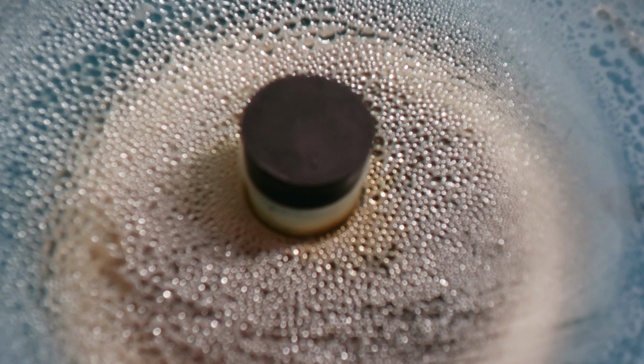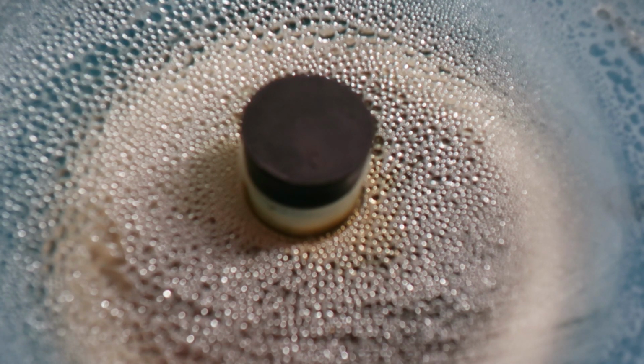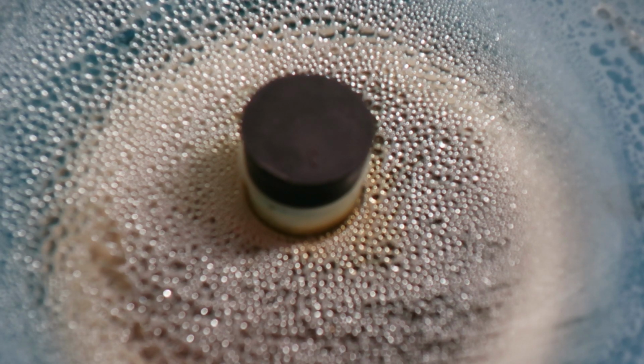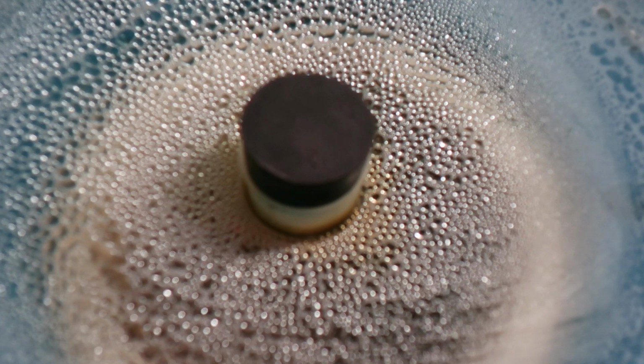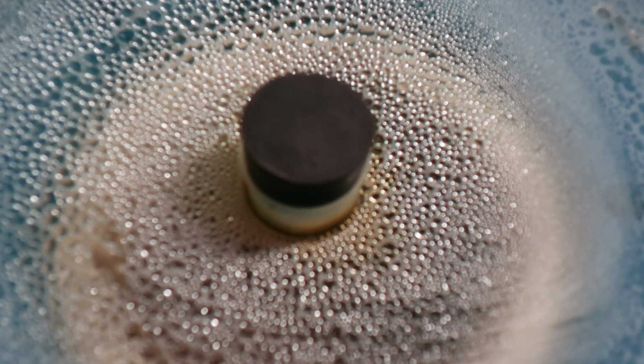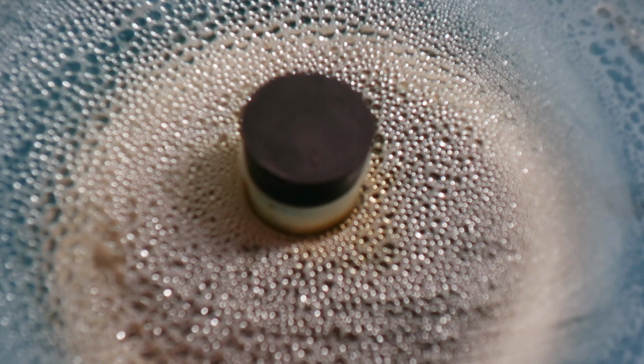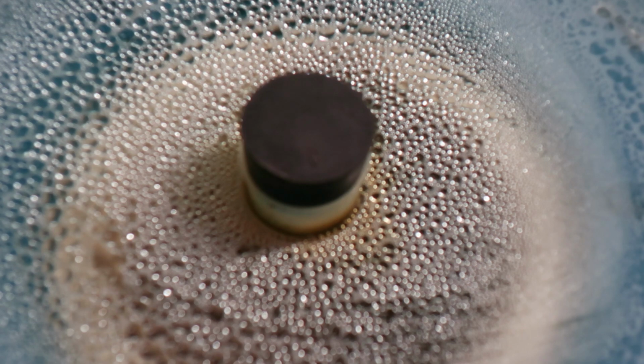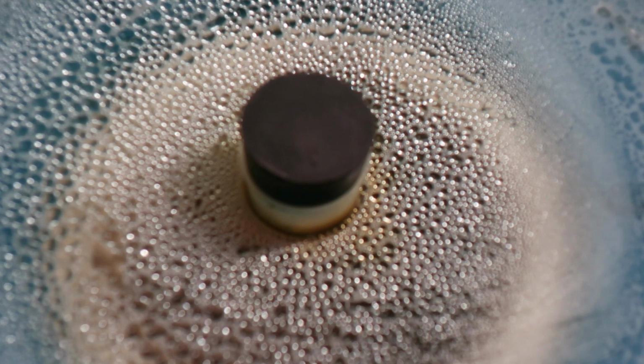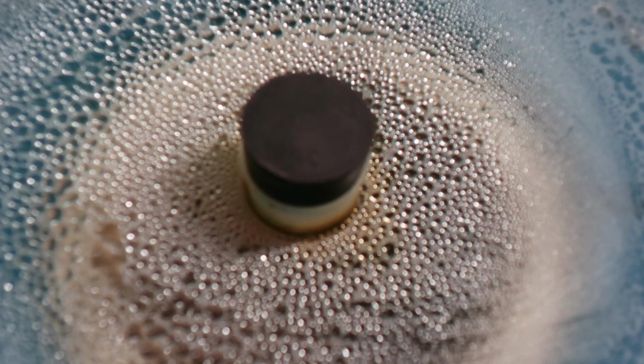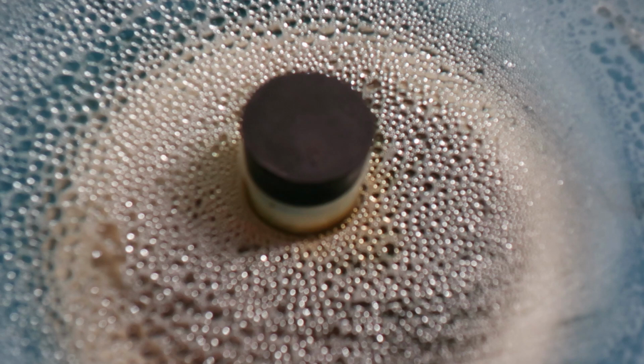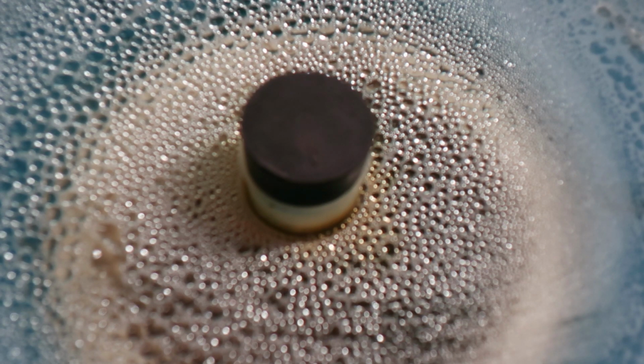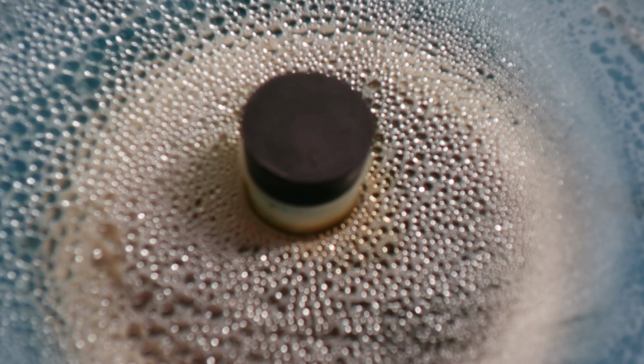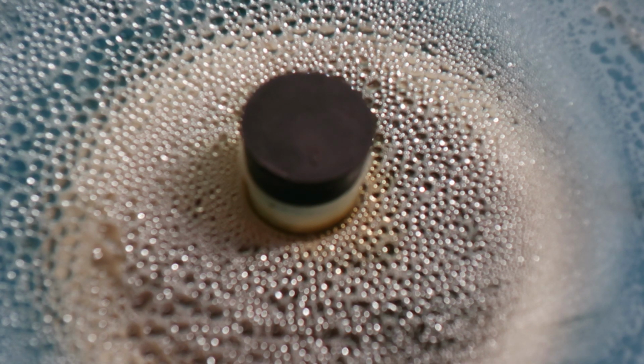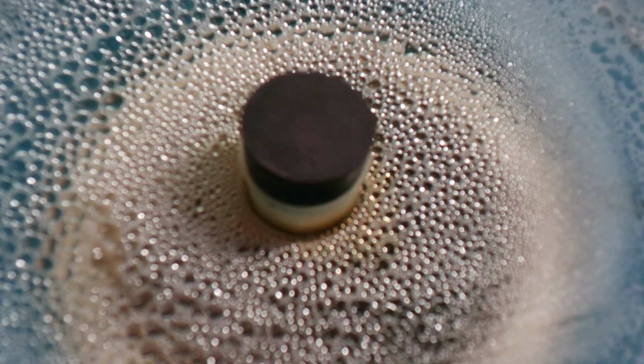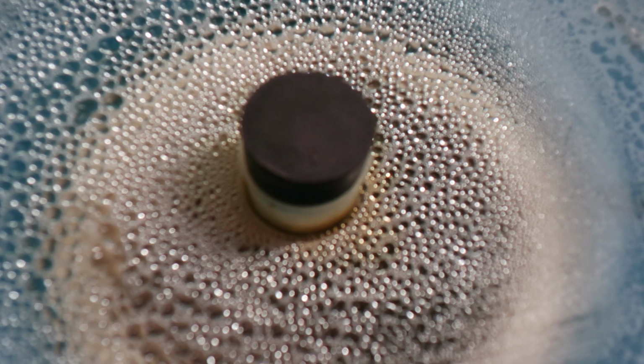So the pot's getting up to 918 degrees. We should be at full temperature pretty quick, but I bet it's going to take probably an hour, maybe a little longer, for all the zeolite to get up to temperature, and I'm hoping that will accomplish it. But it's amazing to watch all that moisture coming out of it, because when you hold or touch it, it seems dry as a bone. And this vacuum chamber I've been running every day, so the moisture is not coming out of the vacuum chamber. That vacuum chamber is bone dry from the last heat. I have tried it once with no zeolite in there and put the glass on it, and there was no condensation. So the condensation is definitely from the zeolite.